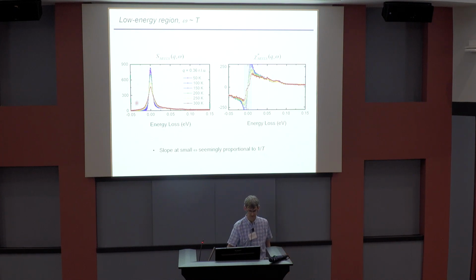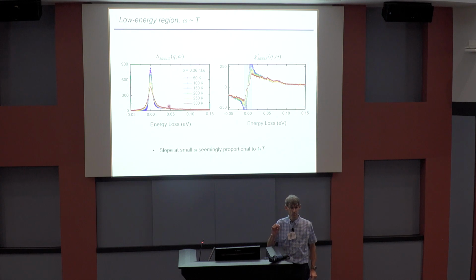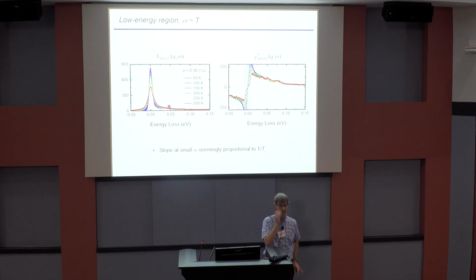But what you can see is something rather unexciting. There's a peak at 0 frequency, and the width of that peak is temperature dependent. So this is sort of normal diffusive dynamics, relaxational dynamics in a liquid. What you get is a peak centered at 0, and then as the scattering rate changes, the width of that peak changes. So it's a good measure of the scattering rate.